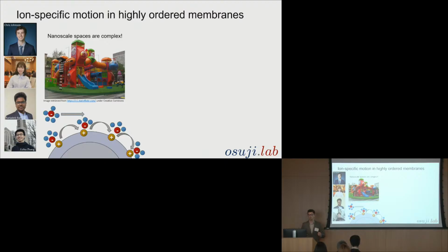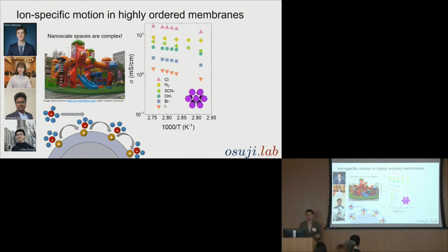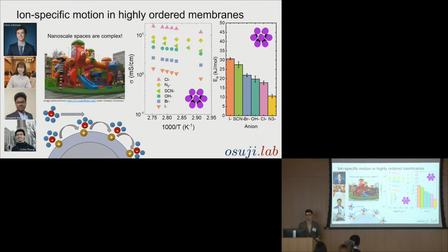There exists a balance between materials that will move through as if they are moving through with water, and then there will exist materials that are clinging to the walls, running along. It's a balance, and we want to see if we can use it to solve the engineering problem of separating out complex mixtures of ions. So if you have sodium bromide and sodium chloride, could the bromide and the chloride be separated? So we measure the conductivity of different types of ions in the hexagonal membranes and the activation energy, which is effectively a measure of how hard it is to get that ion moving initially.